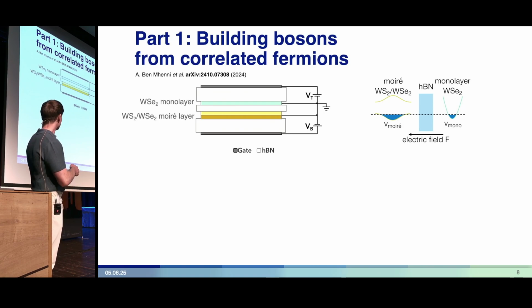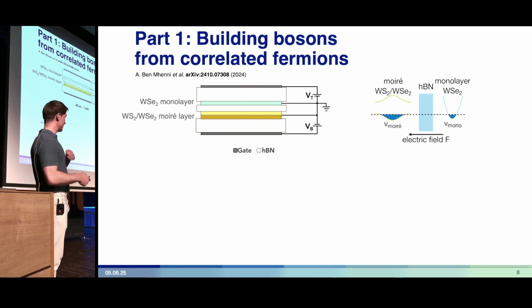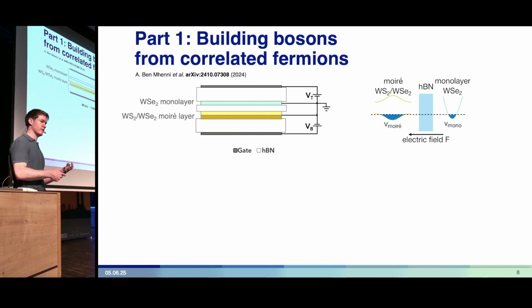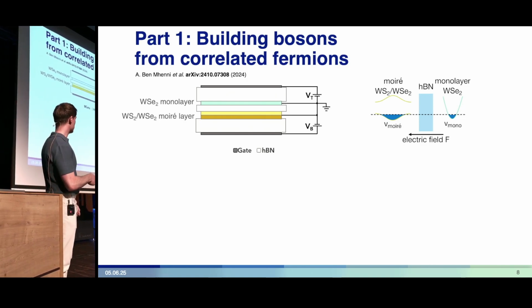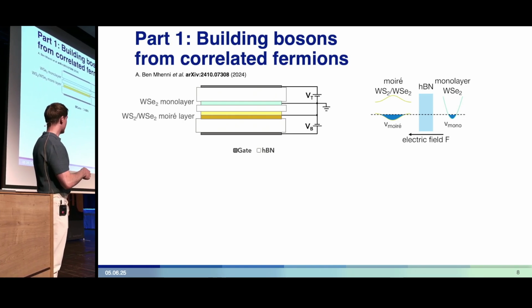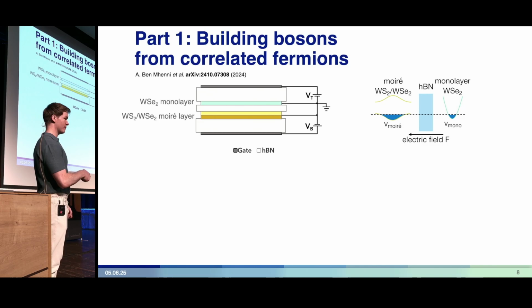I take the bilayer electron system and embed it in a capacitive structure with both a top gate and a bottom gate. Having both gates means I can independently tune the chemical potential and the electric field in the bilayer electron system, which means I can effectively control the charge density residing in the Moiré layer and in the TMD monolayer.